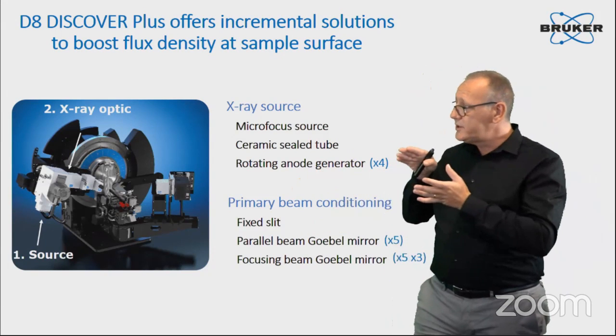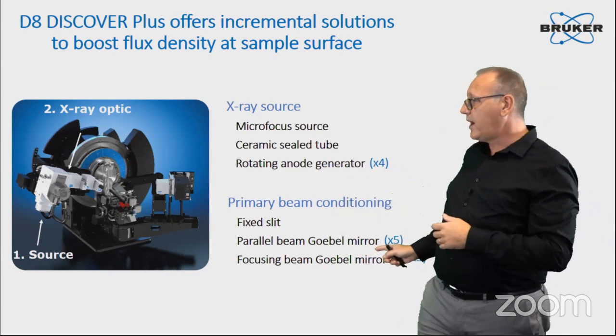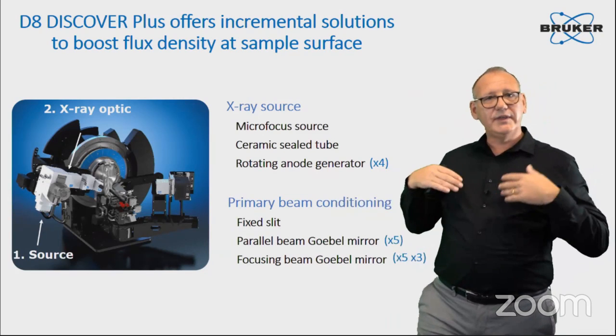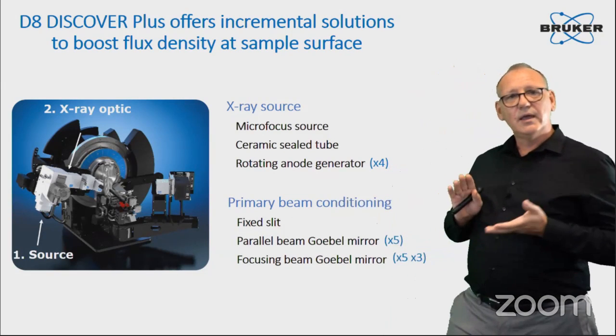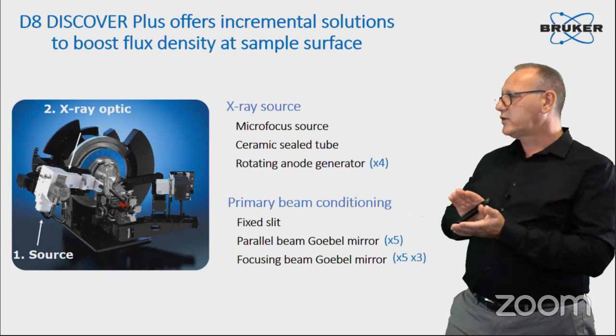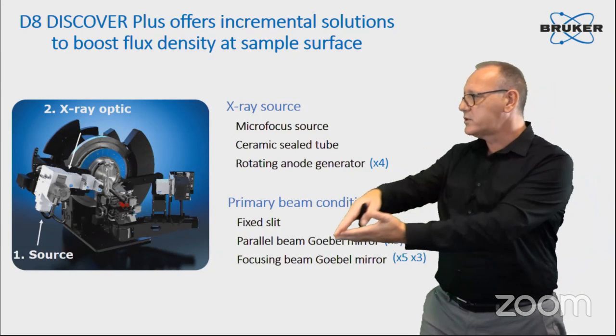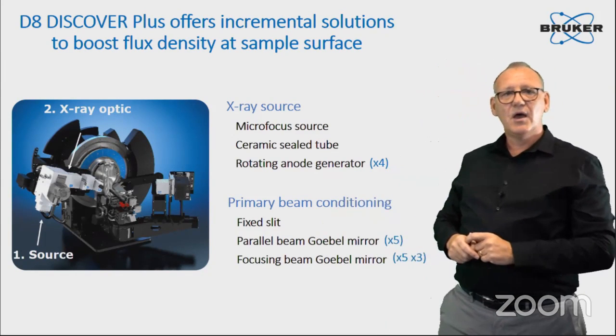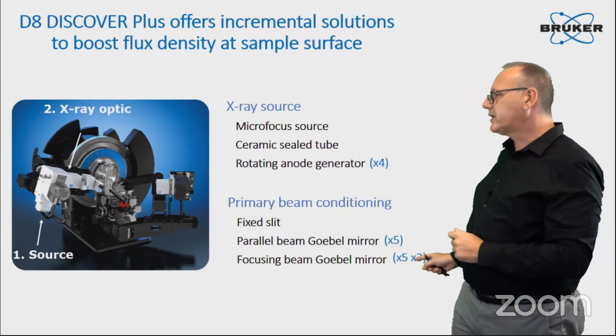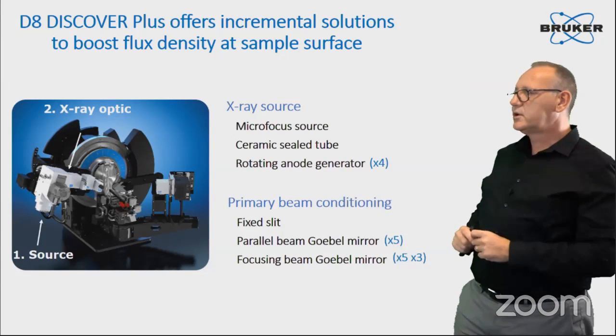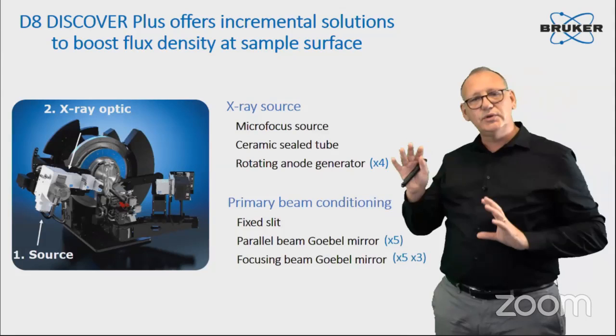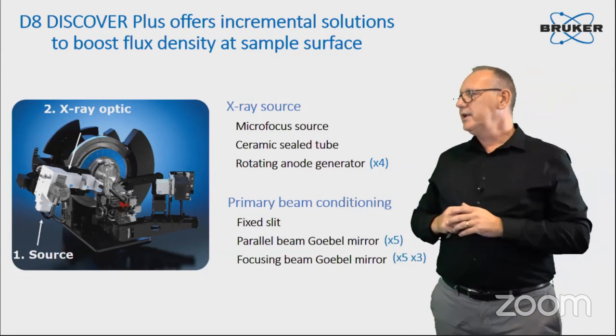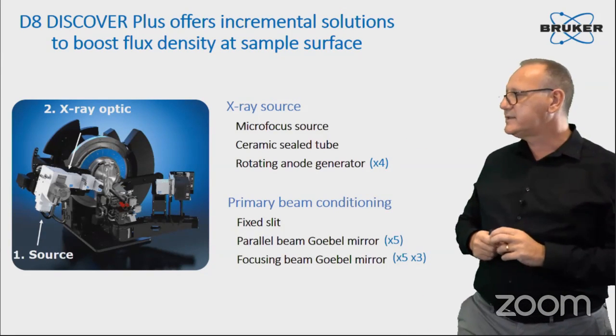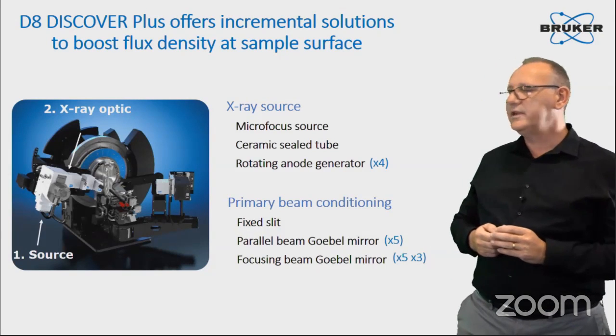So you will increase your flux density by a factor 5. And if you want to have even more flux, you can use a focusing mirror that will convert the divergent beam into a focusing beam at the sample surface. Compared to the parallel beam, that's another factor 3 on top. So you see many ways to tune your configuration in order to achieve the best flux density for ultra-thin film investigation.